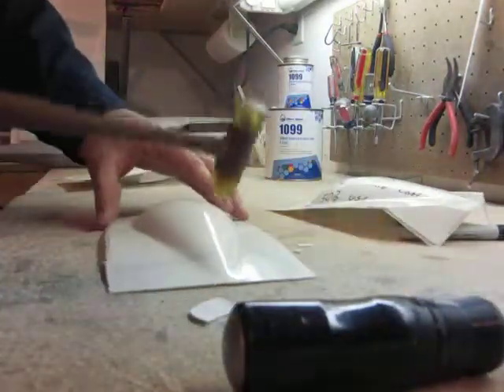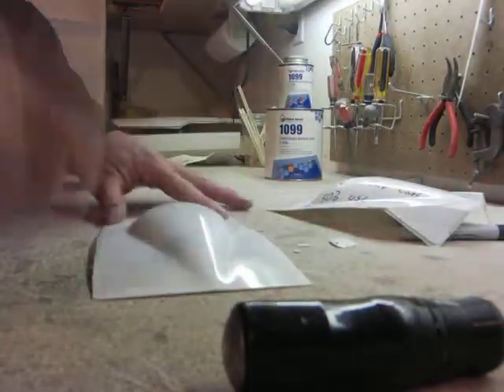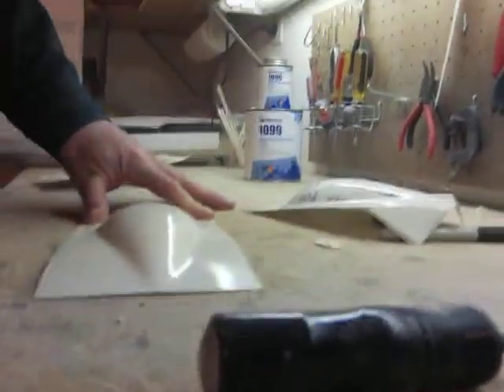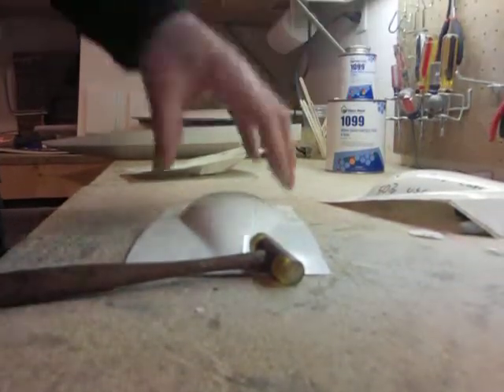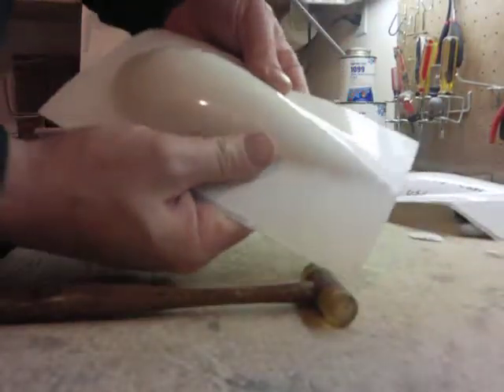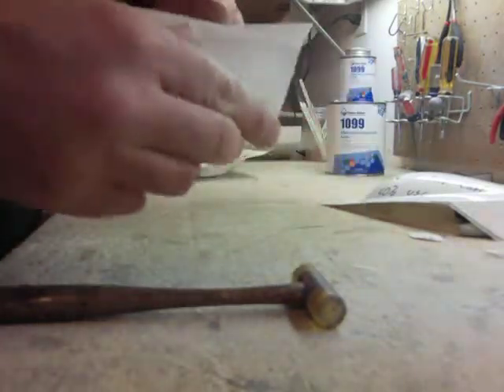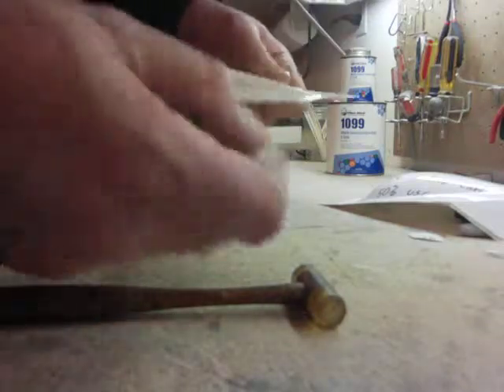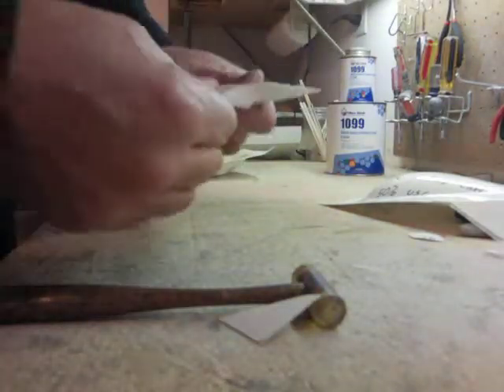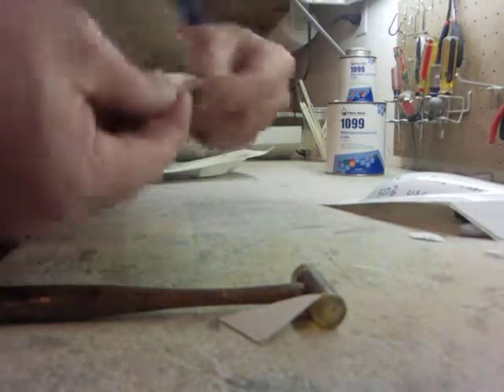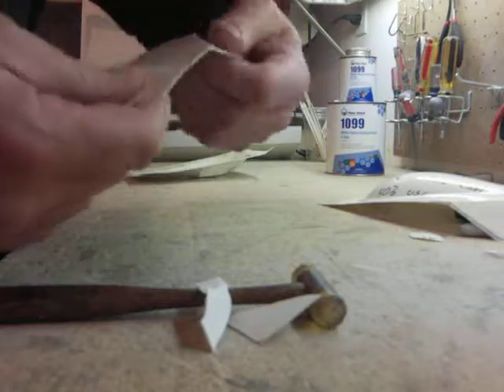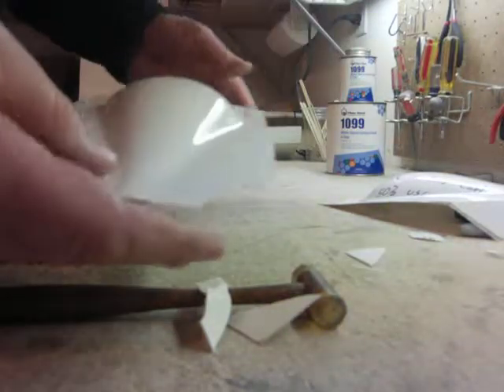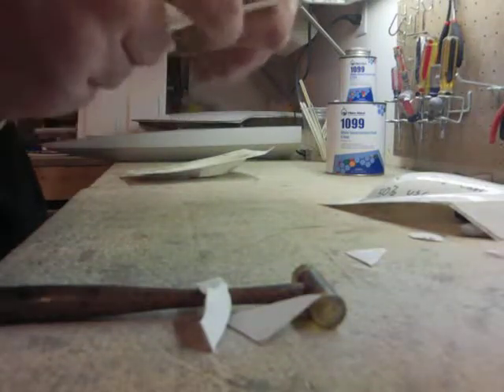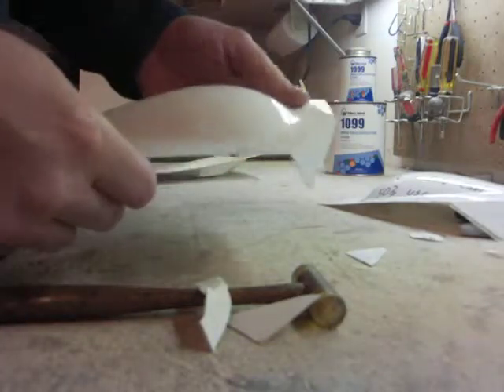So let's take the 4-to-1 ratio, 20% epoxy. Oh, broke the camera. All right, gotta be a little careful here, I guess. All right, once again here, fractured the gel coat, no separation. Crease it in half, no flaking. I can't get a piece of the gel coat, or the tooling coat, surface coat, to break free. So it did not. Ow. Looks pretty good, actually.